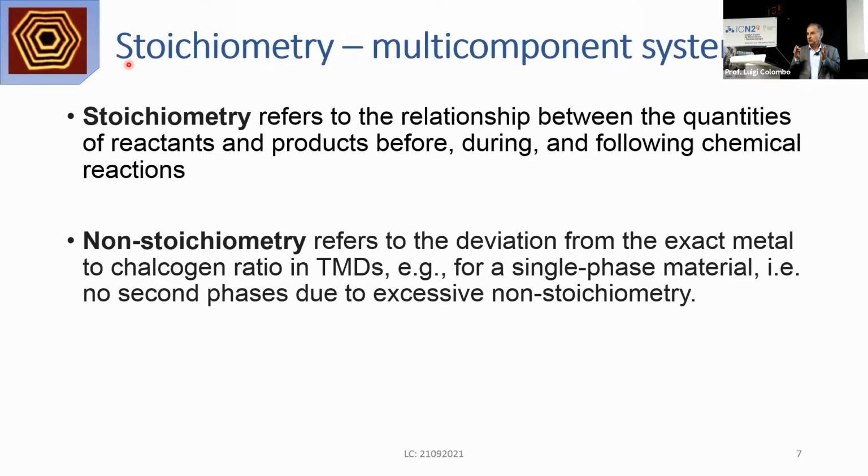That's a huge number. And I think that the reason you can actually have that kind of high concentration of vacancies is because of the two-dimensional nature of the material. In the case of II-VI compounds, for example, like mercury cadmium telluride, you can have as much as 10 to the 19th vacancies, while still being a single-phase material at high temperature. But as you go to low temperature, that equilibrium vacancy concentration decreases. The same thing is true, I think, for molysulfide.